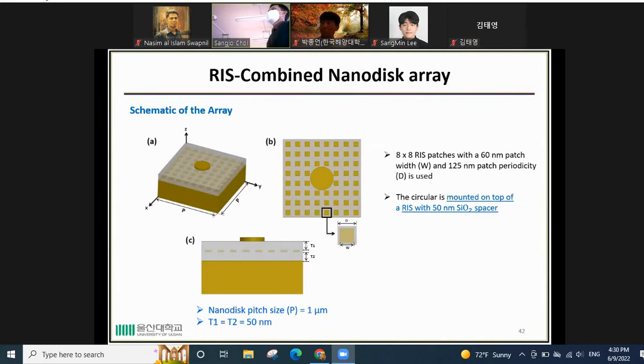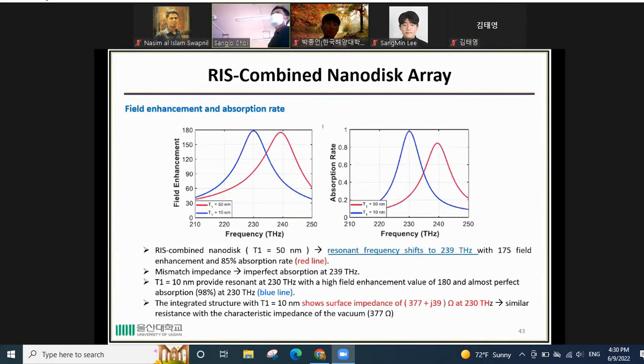After that, we combine the optimum nanodisk parameters with the RIS, and this is the schematic of the array. So 8 by 8 RIS patches with 60 nanometer patch width and 125 nanometer patch periodicity are used. The circular nanodisk is mounted on top of the RIS with a 50 nanometer silicon dioxide spacer. And this is the electric field enhancement and also absorption rate of the combined structure. We can see that with T1, which is the spacer between the nanodisk and patch array, the resonant frequency shifts to 239 terahertz with 175 field enhancement and 85% absorption rate. This is because of the mismatched impedance. That's why it shows imperfect absorption at 239 terahertz.